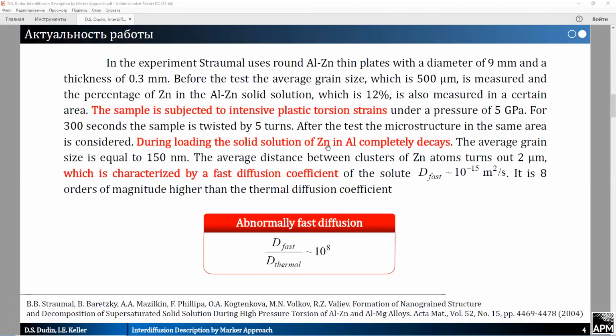We start with the following experiment. An aluminum zinc alloy sample undergoes intensive plastic strains. During the test, a strong grinding of the grain size and an abnormally fast decomposition of the aluminum zinc solid solution were observed. The decay rate can be estimated by a diffusion coefficient 8 orders of magnitude greater than the usual thermal one. The goal is to determine this fast diffusion coefficient depending on the usual thermal diffusivities.